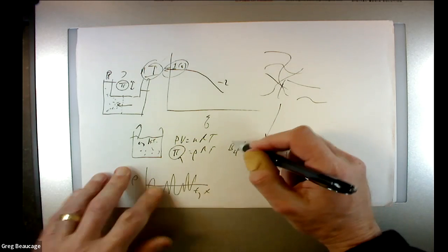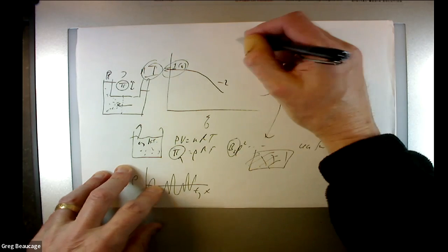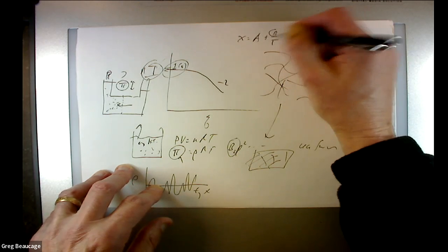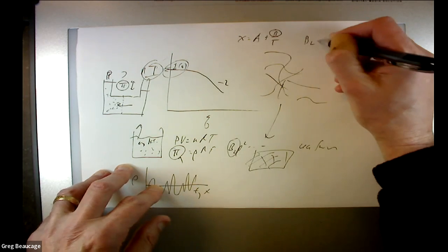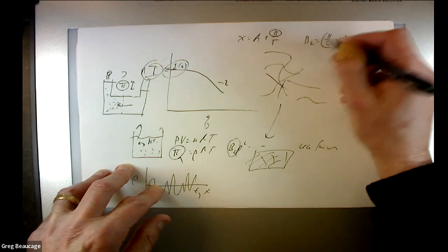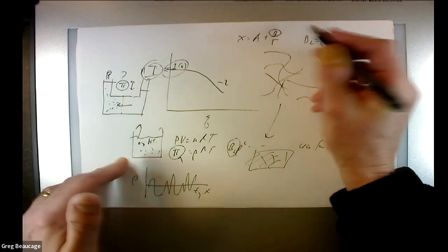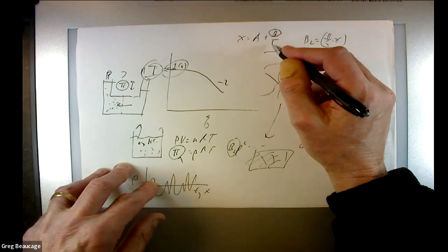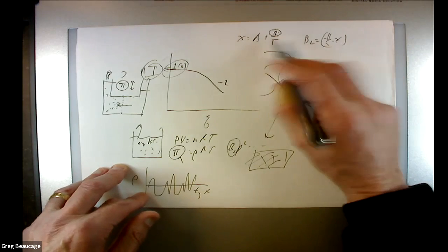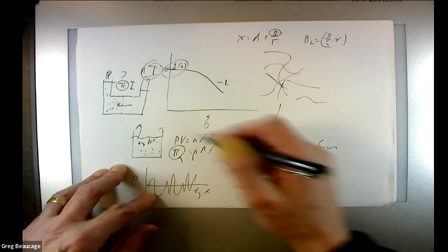Oh yeah, that was one thing that group 2 or whatever did. That B, when you have chi is A plus B over T, that's not the virial coefficient. In fact, B2 for polymer is a half minus chi. So that isn't the virial coefficient. That's just some letter B that they stuck in there. It's commonly called AB, but that's not the virial coefficient. Basically, they're two different things.